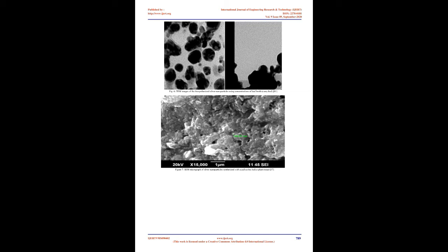Ya et al. 68 had synthesized AgNPs by using gelatin as a reducing agent and stabilizing agent. The obtained AgNPs were mixed with chitosan, CS, cross-linked with tannic acid and then freeze-dried to obtain a new composite gelatin/CS/Ag, which has a dense pore structure with a pore size of about 100 to 250 µm. Gelatin/CS/Ag composite could have antibacterial and wound-healing properties and was found to be a good biocompatible material 68.